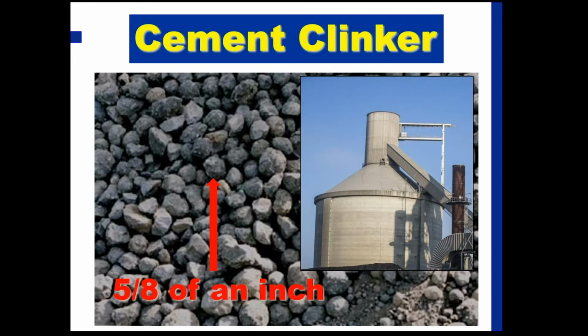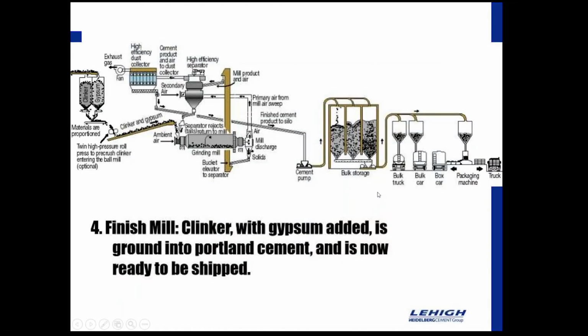And then those go into some internal storage. We want to store our clinker inside and keep it free from moisture. And then from there, we have clinker that we produce, and now we add our gypsum, and that gypsum is added to moderate the set of the cement once it's added to water. So if we didn't have gypsum when we ground our clinker, it would just flash set, and then it would be of no good to anybody.